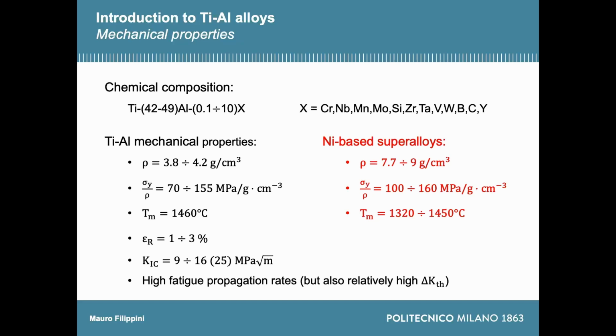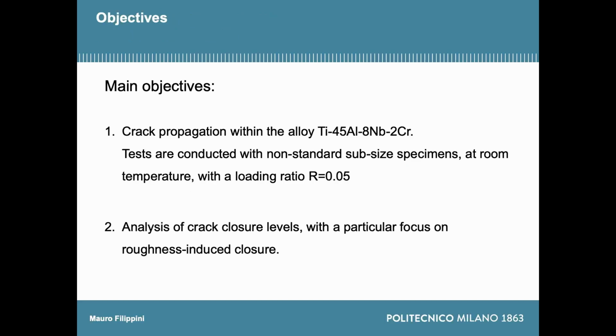The main drawback of these materials is that they are quite brittle. So the strain to failure at room temperature is in the range of 1 to 3%. And the K1C, so the fracture toughness, is relatively low. So you have a relatively high delta K threshold, but the difference between the delta K threshold and the K1C is very narrow, is small. So this reduces the design space very much.